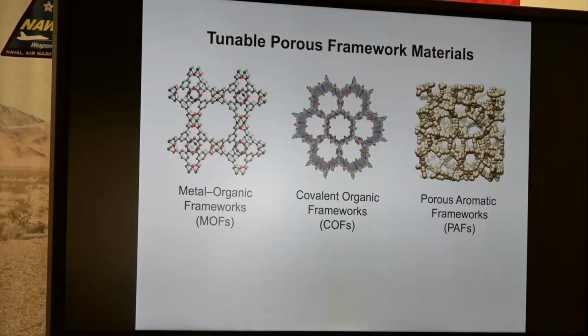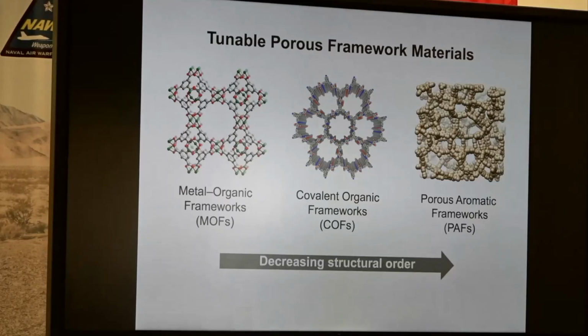And so broadly speaking, these can be classified into these three groups. At the left, you see an example of a metal organic framework. In the middle, covalent organic frameworks. And at the right are porous aromatic frameworks. And there are differences in these. All of these have molecular design possibilities. But metal organic frameworks are highly crystalline materials with perfect discrete pore sizes. Covalent organic frameworks are usually less easily crystallized. And then porous aromatic frameworks that are built up of only very strong carbon-carbon bonds, these tend to be amorphous network solids.